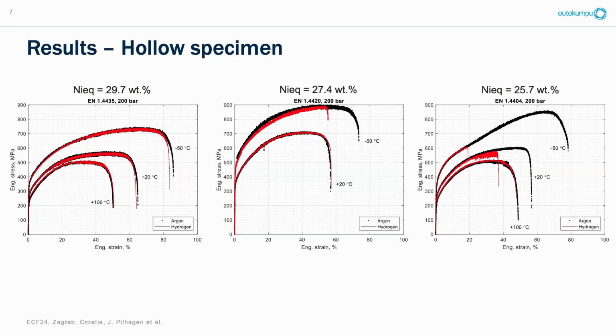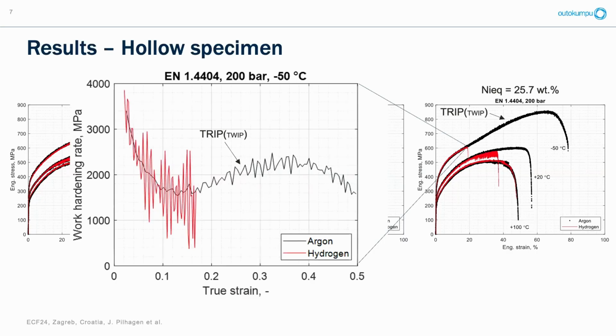You can also see that at around 20% engineering strain, the strength starts to increase rapidly. That's because of the TRIP or TWIP effect in the material. And that's even more evident if you look at the work hardening rate, as you can see in this figure. The bump here comes from the activation of martensite formation and mechanical twinning. We can also see that in the hydrogen atmosphere, it actually breaks when this kind of strengthening mechanism starts to kick in. So that's also a good indication that it's related to the stability of the austenite.